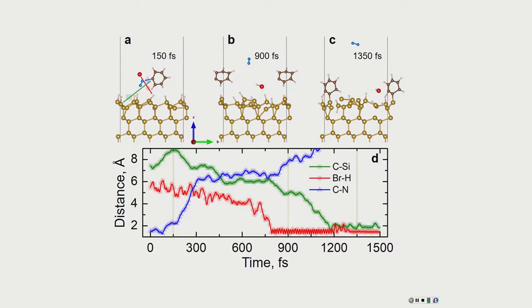What did you call the salt? Diazonium. If you see what Yulun is showing, it's a phenyl benzene ring connected to two nitrogens. If you construct it this way, it will be charged, and in order to compensate the charge, you need an additional anion. So this is a cation and an anion, so it is a salt. And when you try to evaporate, sublime, or deposit it, it decomposes and actively tries to bring the phenyl group to anything.